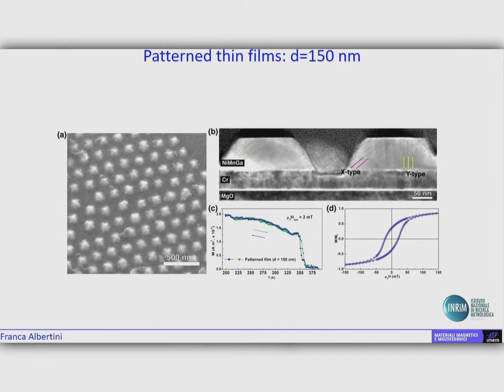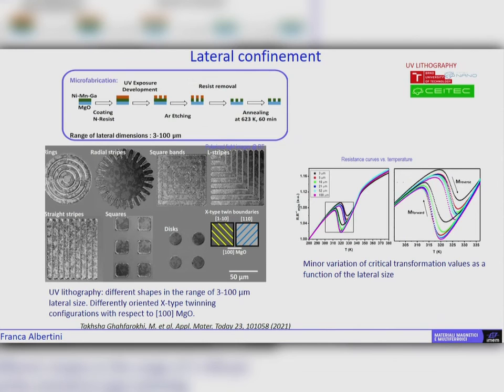We have also obtained smaller materials and checked the properties of the materials and also studied microstructure. And we have gone on with this research to make a more general research, including studying the effect of geometry and size of patterning. So we have used electron lithography and also optical lithography, UV lithography. In this case, we have obtained materials down to 3 microns with different shapes. And by checking resistance of these materials, we have found only a minor variation of the critical transformation as a function of the lateral size of the material.